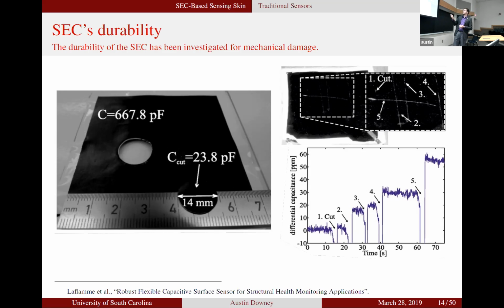Yes. So like on these damages here, like at 40 seconds, if there was a fatigue crack that opened in between, we'd see a signal. You're not going to be able to tell the difference between the two unless you know that there wasn't somebody out there cutting it. But you can paint over these sensors. We had a sensor that was deployed for 5 years on a bridge in Iowa. This bridge got painted, so they ripped down our data acquisition system, brought the sensor back into the lab, glued it onto a plate with the green DOT paint on the sensor, and it still works just fine. But that paint would definitely change the value of the sensor.